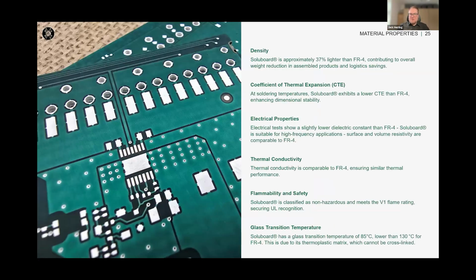So technically, Soluboard does hold up. We are 37% lighter than FR4. We also have strong thermal and electrical properties compared to the likes of FR4. We tend to sit somewhere in between the likes of CEM-1 and FR4 in terms of our electrical properties. One of those, for example, is our CTE, our coefficient of thermal expansion. This is slightly lower than FR4, which does allow us to have more dimensional stability, which I'll expand on. And we're also now UL recognized, and I can expand on a few of these tests here.